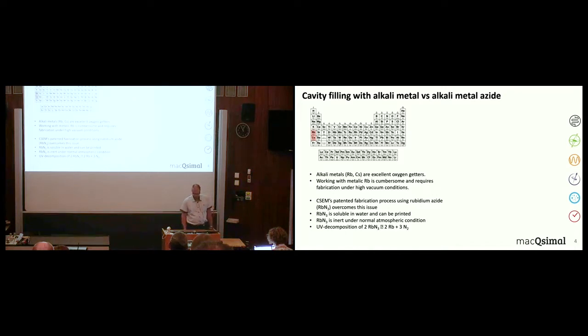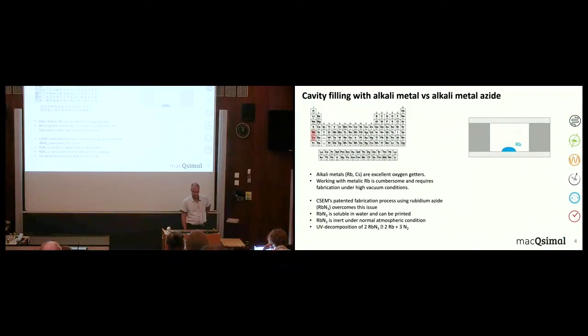One issue in fabricating a vapor cell: the most straightforward idea to make a vapor cell would be taking a wafer with a cavity going through, putting a glass window on the backside, putting the metallic rubidium inside, and then closing the cell with a topside glass. Unfortunately, alkali metals are very good oxygen getters, and once the rubidium or cesium is oxidized, it is not available anymore for spectroscopic application. So this fact makes the filling directly with metallic rubidium or cesium very cumbersome, because all this has to be done under very high vacuum conditions.